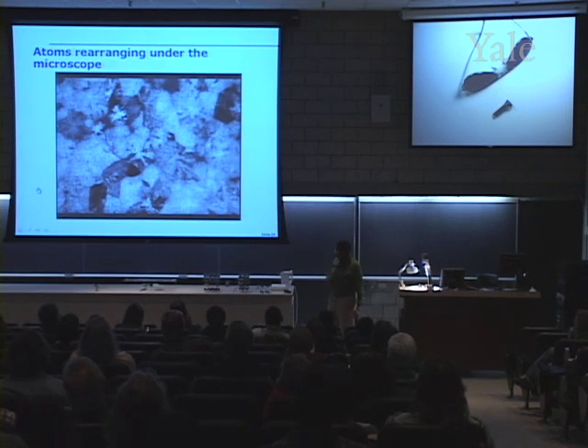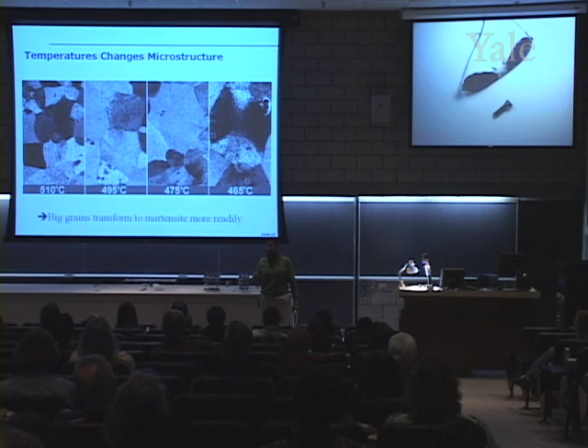And so the experiment that I'm interested in doing is looking at how we can heat these materials up at different temperatures and what's the final structure look like. Well, let's look at those kinds of images. Oops. Give me some control. Here is an example of films that have been heated to different temperatures and they have different grain size. The temperatures are indicated at the bottom. 510 degrees, that's our high temperature case. 465 degrees, which is our low temperature case. If you don't recall what C is and how that relates to Fahrenheit, just multiply these numbers by 2 and add 30. That's an approximate for how hot it is. These are fairly high temperatures.